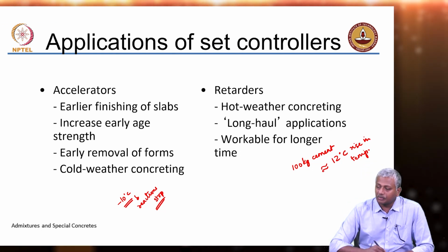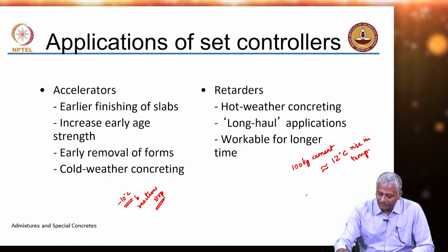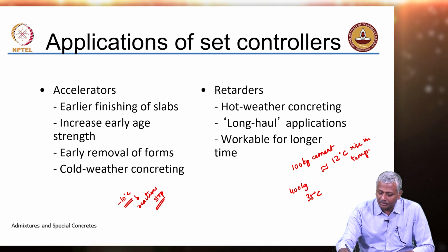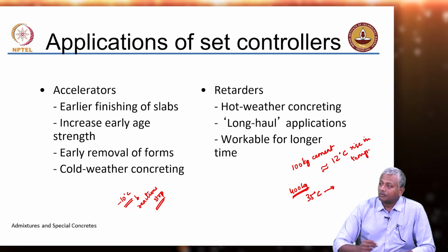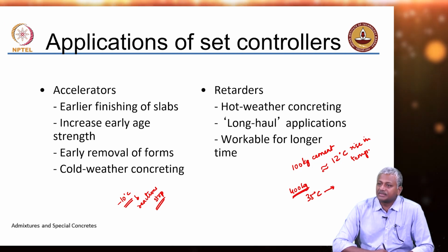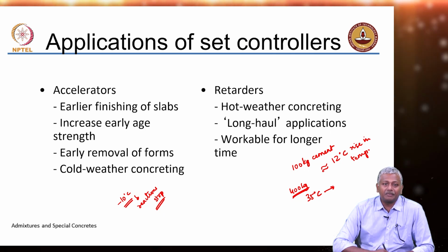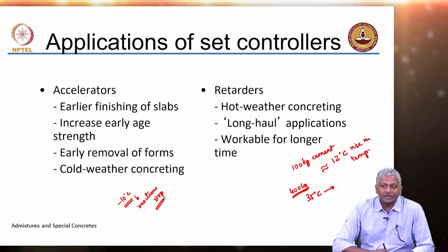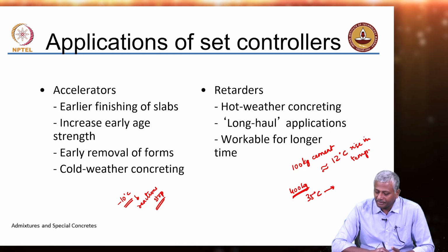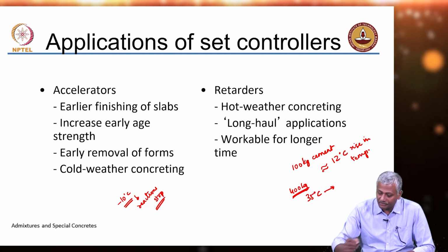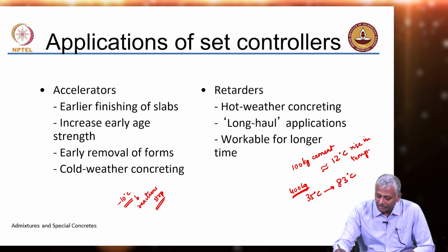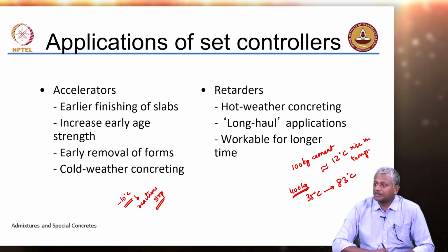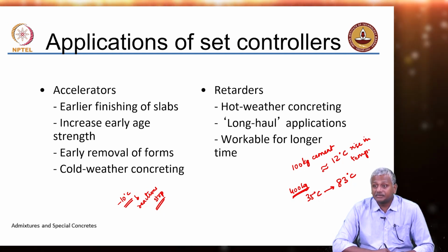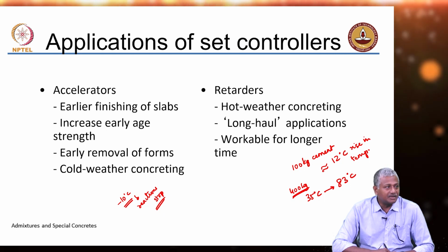So, if you start your placement of the concrete at 35 degrees Celsius and let us say you have 400 kilogram of cement in your mix, what is the temperature rise or what is the temperature of the concrete that can be expected? The peak temperature: 35 plus 4 into 12, 48, 83 degrees can be the temperature of the concrete, 83, right.